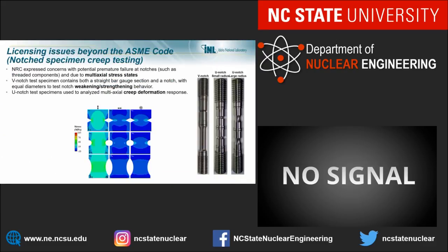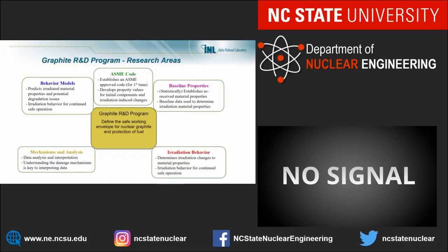Some of our specimens are for multi-axial, weakening strength, creep deformation. So these are some of the specimens we use, some of the profiles that come from these specimens. We have a graphite program. Now, the core and the fuel, where the fuel rests, and the reflector blocks of some of these gas-cooled reactors are made of graphite blocks.